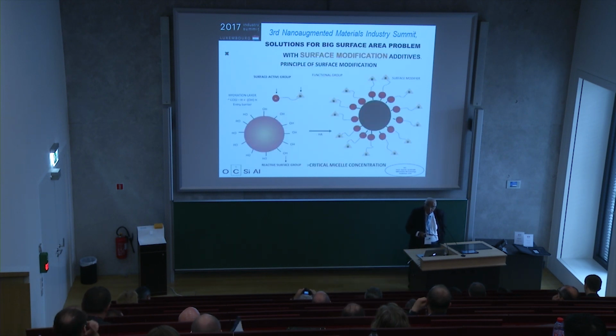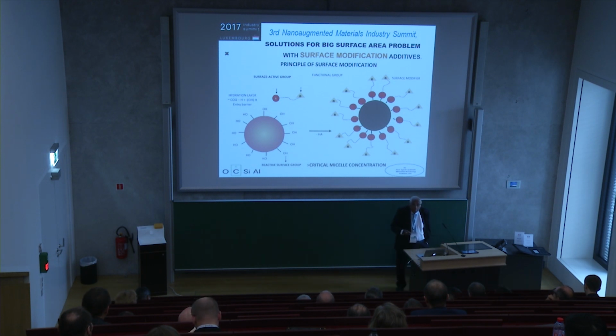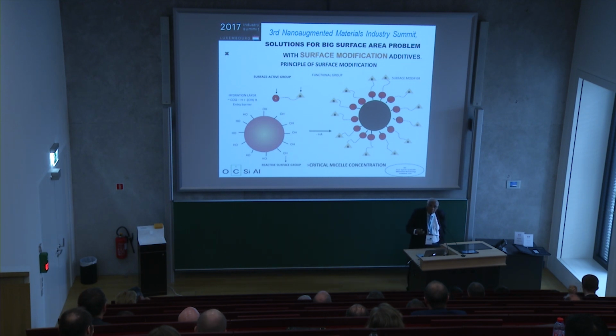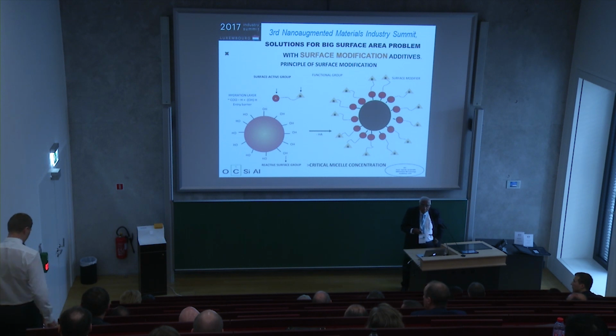So here we have the stabilization of the particle. We have surfactants, naturally occurring surfactants in natural rubber, and you will find that when we first centrifuge the latex from the field latex, where we are raising the concentration from 40% to 60%, the mechanical stability of the latex drops to about 200 seconds. And then over a period of 3 weeks, the mechanical stability rises to almost 4 to 5 times the original value. Because what happens is that there's a hydrolysis of various non-rubbers like the lipids, etc. And these form higher fatty acids which take over the role of long-term stabilization of the latex. So our stabilization systems for dispersions must be compatible with the naturally occurring stabilization systems.